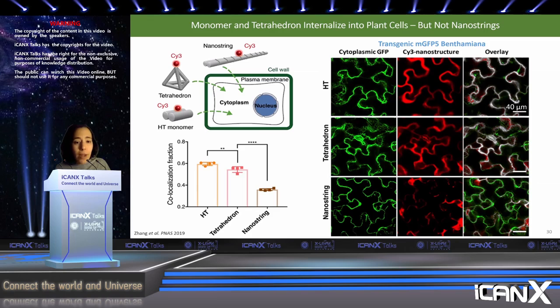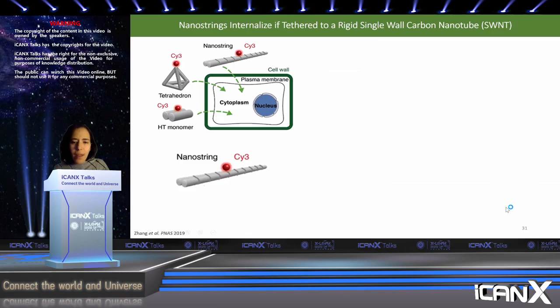However, it was surprising to us to see that in terms of colocalization fraction, these nanostrings actually internalize less than the tetrahedra and hairpin tiles, again, as assessed through this colocalization assay. And so we were perplexed by these results, and what we did to test the effect of other parameters was